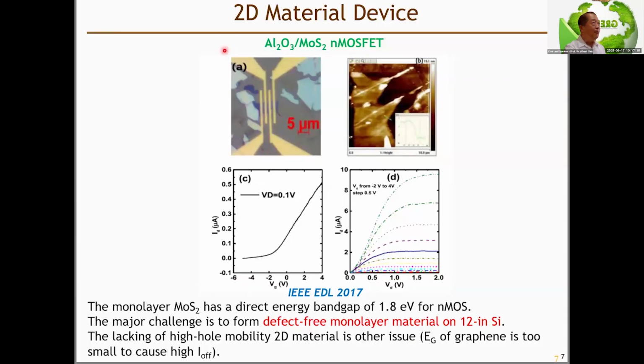And here shows the problem of a two-dimensional (2D) material, for example, molybdenum disulfide. The single atomic layer molybdenum disulfide has a direct energy band gap of 1.8 eV, which is perfect for an N-type transistor. N-type transistor means that this transistor will be driven by the electrons.